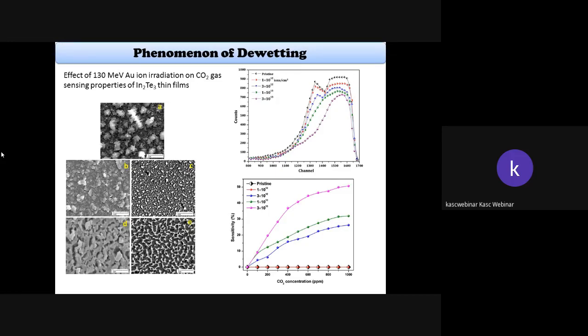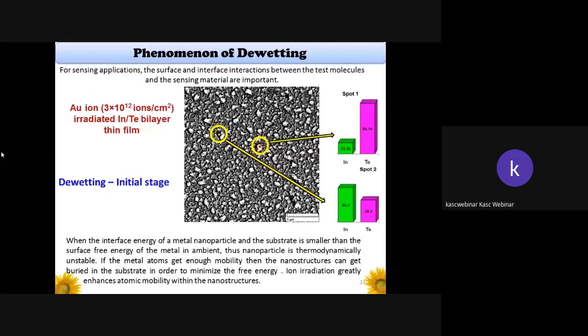But in the case of a conventional method, it's not at all possible to achieve a miscible system, especially in the case of an indium and tellurium sample. And the same sample was tested for carbon dioxide. Actually, the high ion fluence irradiated sample shows a higher sensitivity compared with the pristine sample and the lower fluences. The reason is that, especially for sensing applications, the surface and interface interactions between the test molecules and the sensing materials are also important.